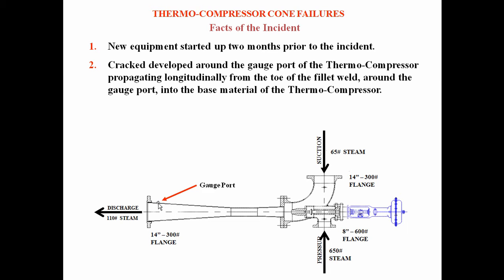The initial incident occurs at this gauge port. Now this is a field installed gauge port. It's a 3/8 inch threaded half coupling that they're using for a thermowell. What happens is a crack develops in the fillet weld of the thermowell, goes all the way around it, and propagates into the base material of the thermocompressor cone. Now this occurred approximately 2 months after startup.